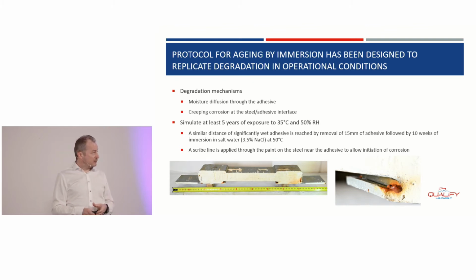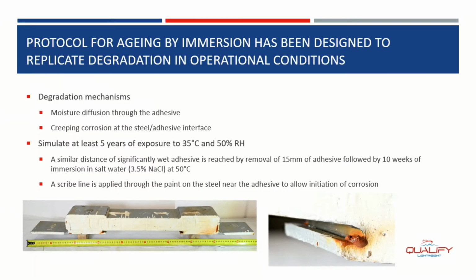Besides that, we wanted to be able to replicate an operational condition of 5 years of exposure to 35 degrees Celsius and 50% relative humidity. We have already spoken about 25 years of total life, but 5 years should be the lifetime in between two dockings of the ships, at which a complete inspection and repainting can start. So this should be the time that lasts without any potential knowledge about corrosion damage.